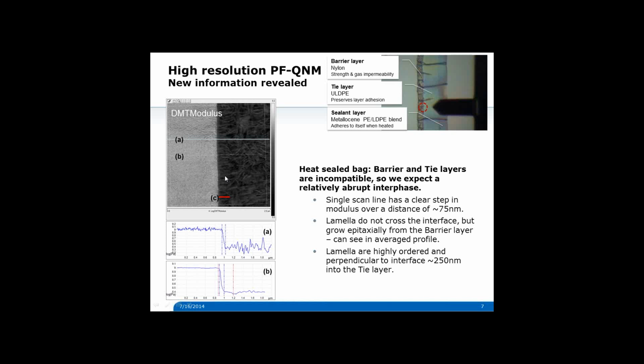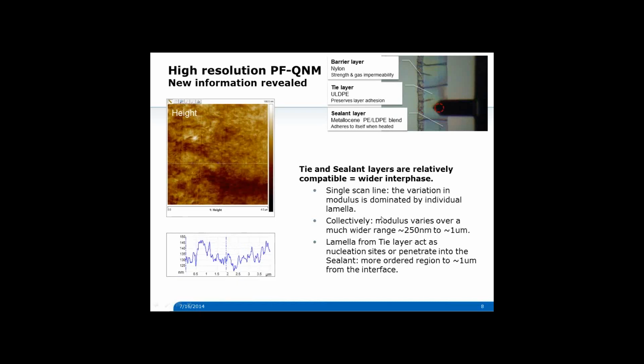If we look at the other interface, the interface between the tie layer and the sealant layer, the first thing we notice is that we have a very good cryo microtome of this sample, and that really there is no signal of any change happening in the height map. So the topography is not allowing us to actually even see where this boundary is.